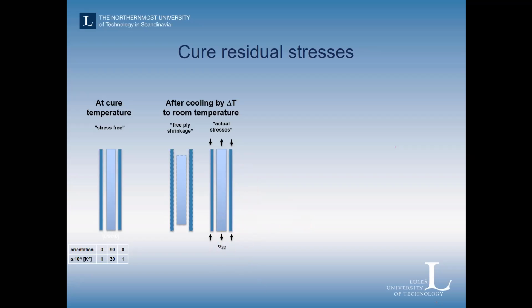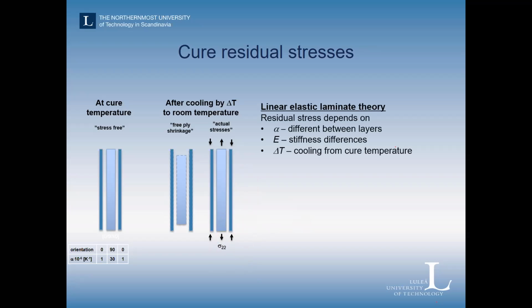So especially the tensile loading on the 90 degree layers is very important and provides very high stresses, and this is what sometimes creates a crack that we observe. If we just take the linear elastic laminate theory, we know that the residual stresses depend on the thermal expansion coefficients, the stiffness, and the delta T. And in this case, the delta T is up towards 300 K, so it's very large.